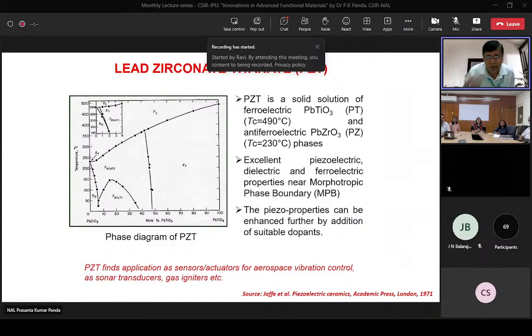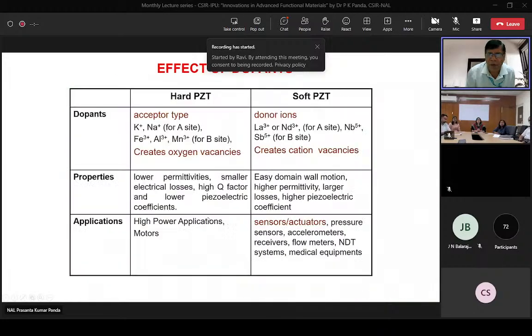Now, if somebody wants to attempt to synthesize PZT material, one is to go by this phase diagram. What is interesting is that it is a solid solution of lead zirconate and lead titanate. At this composition, about 48-52 or 52-48, on both sides, tetragonal and rhombohedral phases coexist. Therefore, this is called the morphotropic phase boundary, and one is to synthesize in this condition. Further addition of dopants will also enhance the properties.